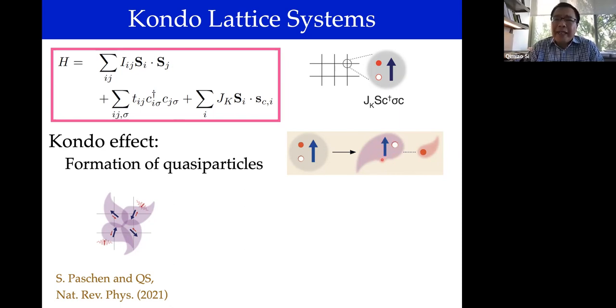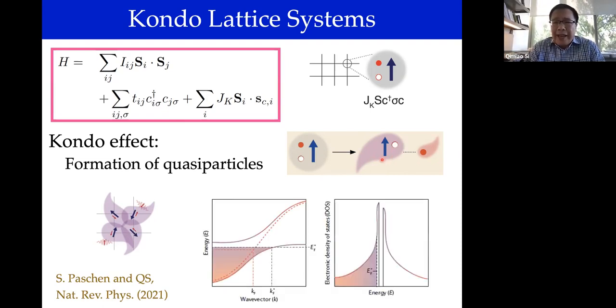So that's in fact the composite fermion, which provides a basis for the heavy quasi-particles, and that's usually encoded in a mean field description of a conduction electron band like this dashed line, hybridizing with a renormalized flat level generated by, which represents electron excitations generated by the Kondo effect, and they form these hybridized bands with very large density of states, and therefore the name heavy fermions.